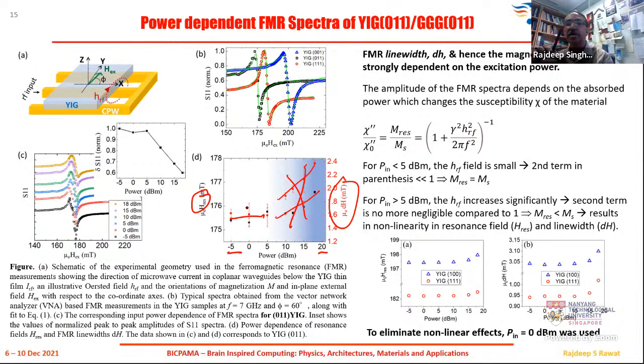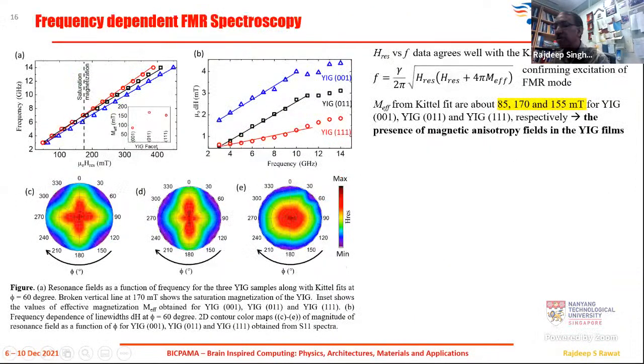As you may remember from Professor Fukuma's slides just before, if the precession cone angle is small, the precession is quite linear and uniform, but when it is large, it does not remain linear all the way. There will sometimes be kinks here and there that bring in nonlinearity. So we wanted to exclude that nonlinearity, and therefore the rest of the experiments were done at 0 dBm. The later results I'm showing are at 0 dBm.